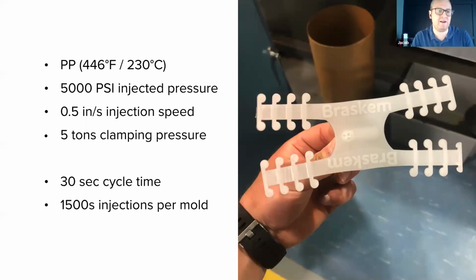This will be dependent on how close of a parting line you can keep, but keep the pressure as low as you can. In the end, we were able to achieve a 30-second cycle time, which is, I think, very efficient and comparable to what a metal mold would be. We were running in semi-automatic, which means we didn't have ejector pins. We had an operator pulling each shot out. This was just because we didn't have time within the 48 hours to dimension out all of those ejector pins.